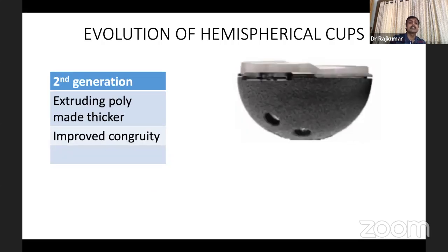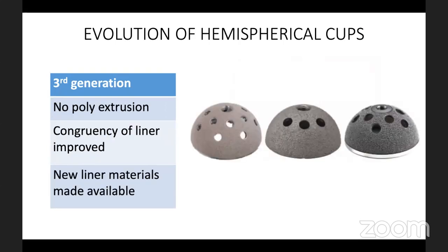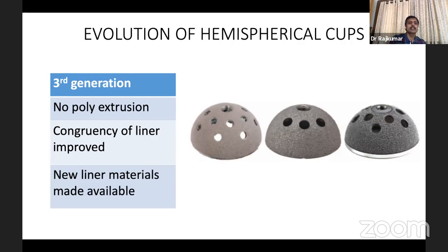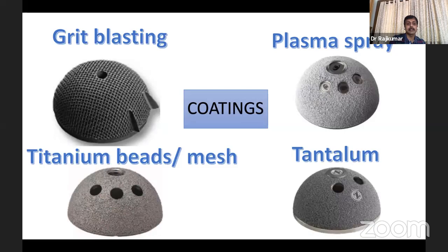In the second generation, congruity improved, the coating became better, the poly protrusion became less, and they made a thicker poly. But in the third generation, there is no poly extrusion. It's a neutral liner, newly highly cross-linked liners are available, and the cups have become hemispherical. In these hemispherical cups nowadays, it is either titanium coatings or tantalum coatings or plasma sprayed or grit blasted. These all help in good stability, fixation, and also help in bony integration, that is the osteointegration.